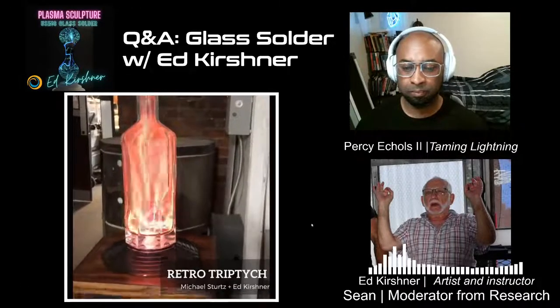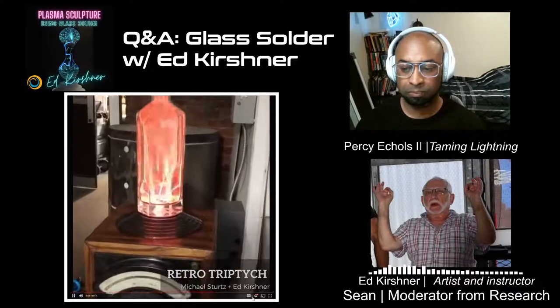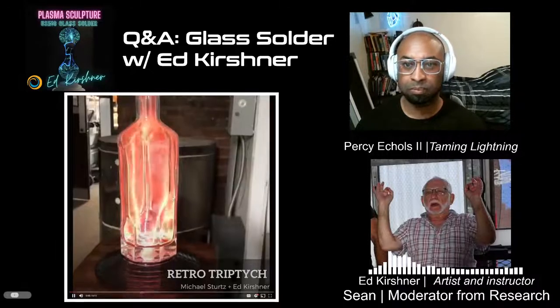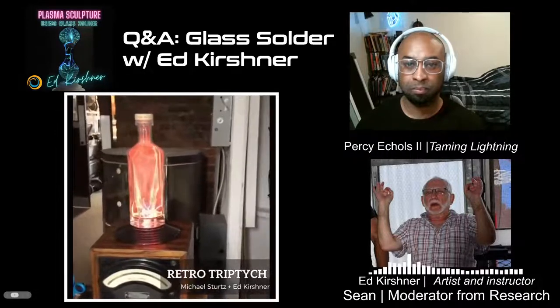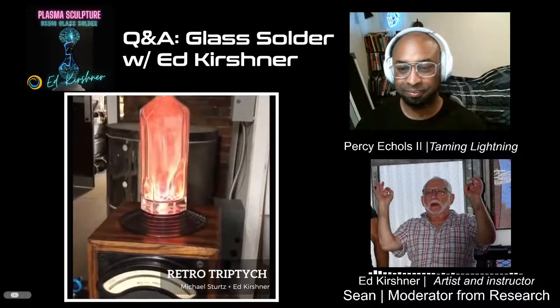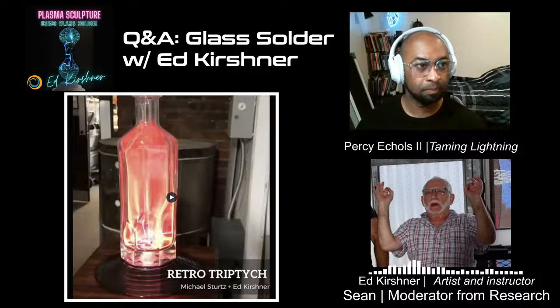This particular one that Percy is showing is a harder glass, and the top is plugged with a glass plug, but that glass plug is cut out of another bottle, just like this. That's smart. So it's the same glass, so the solder works fine with that. The solder has a big range, I would say from 85 to 115, probably. That whole range that we would be working with is fine. The important thing is that the two pieces of glass match as close as possible. So the top was relatively easy to do.